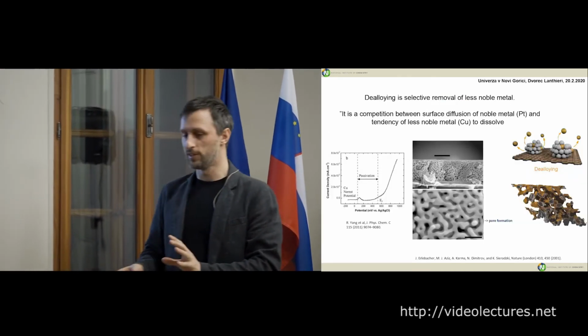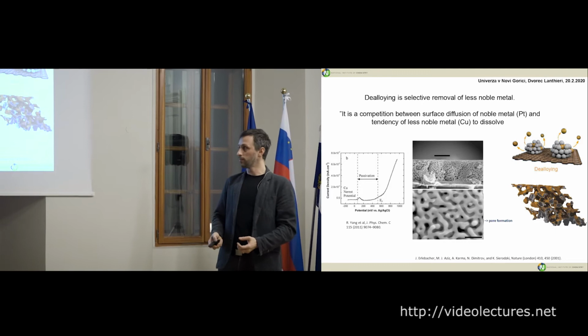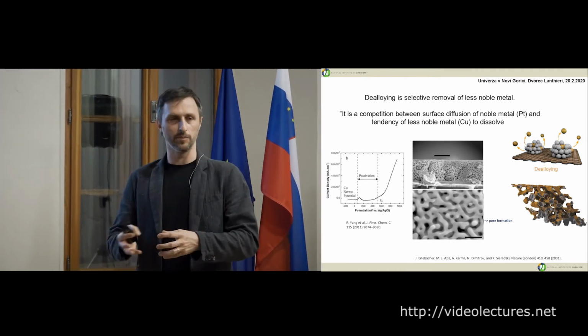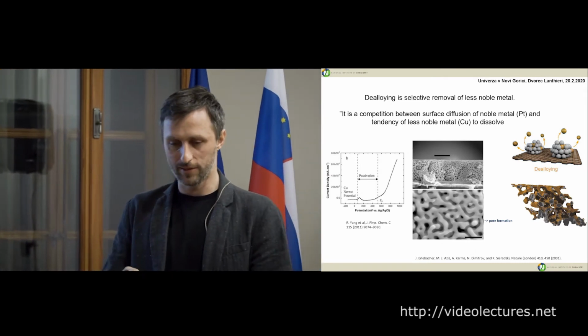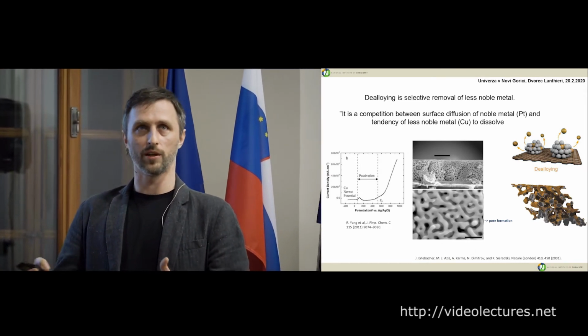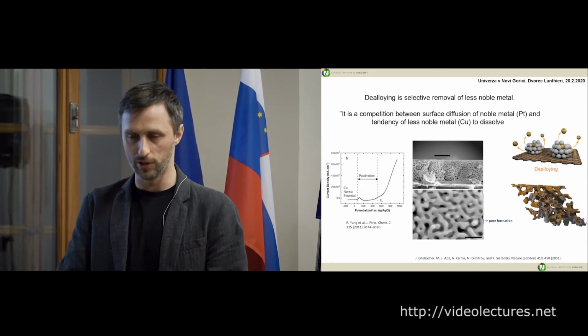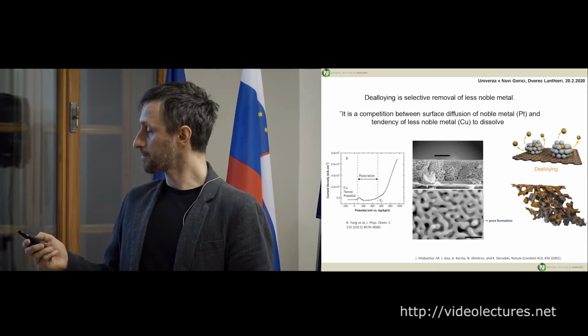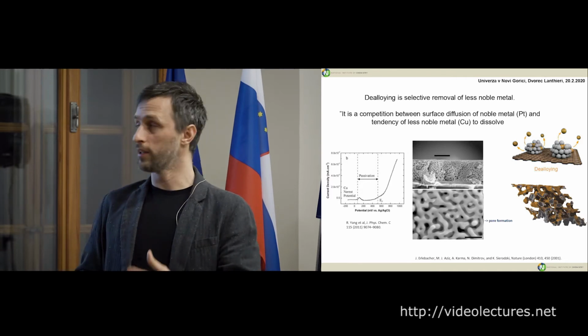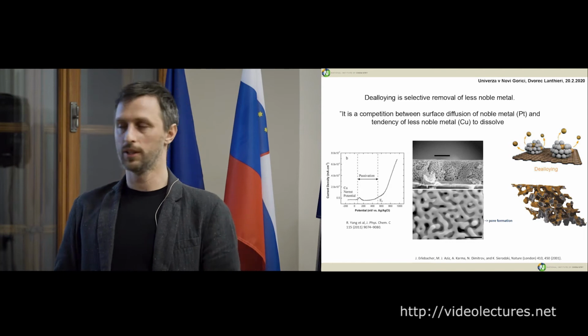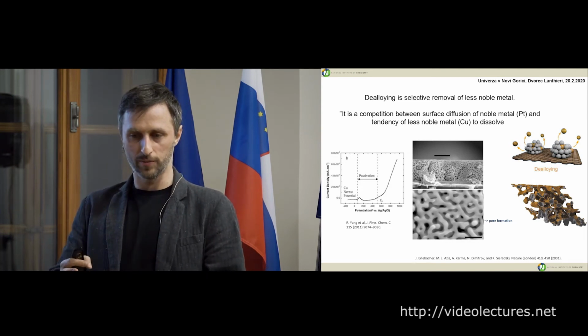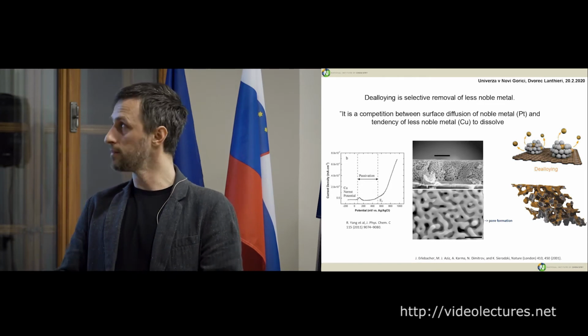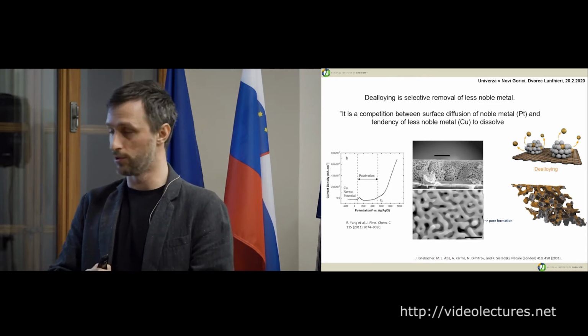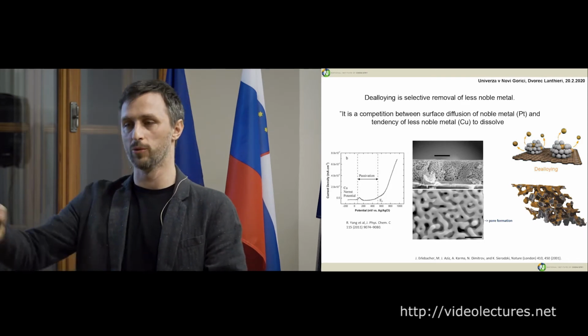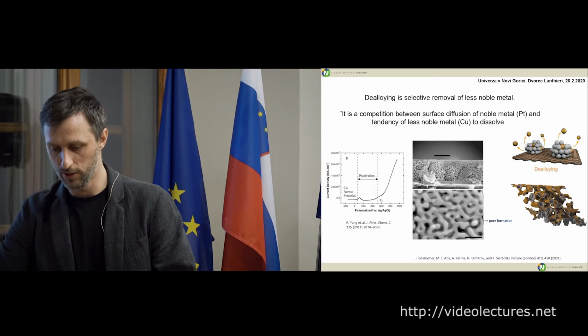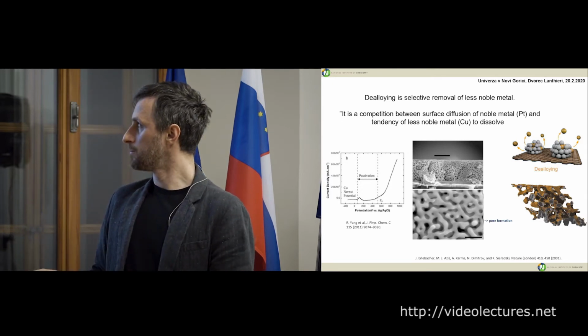Now I want to introduce you to dealloying, which is selective leaching of the second metal, because usually we use platinum alloyed with something else as a good catalyst, but this second metal is copper or nickel or cobalt, which is not stable in acidic media, so it's dissolving. Particularly it's interesting because dealloying leaves behind a porous structure. This happens when you have a high composition of the less noble metal, so there's a critical composition. And if you pass a critical potential, you push it out, so you oxidize it out. So this is the mechanism.